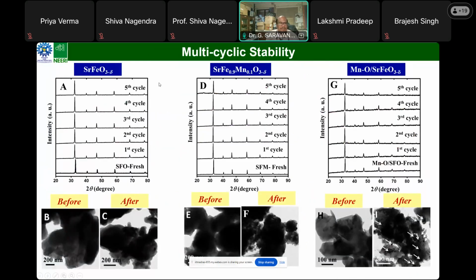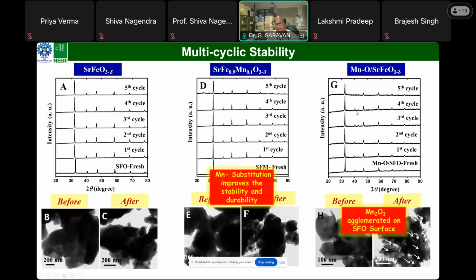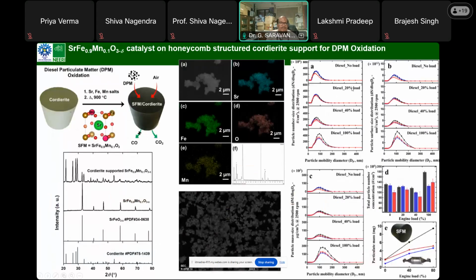So again, we repeated the various cycles. We checked the structural integrity as well as stability, and we found that both the unsubstituted and manganese substituted catalysts are stable. Nothing is happening even after certain cycles. Whereas in the manganese oxide case, the particles got agglomerated on the surface.